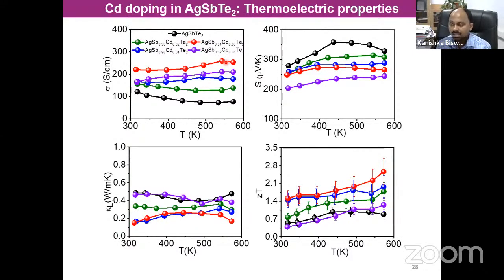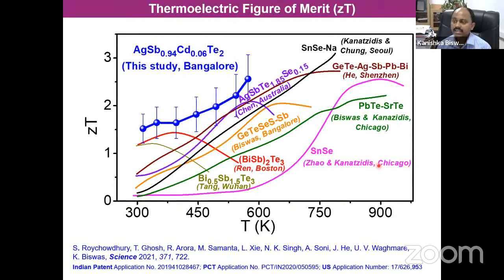And with that, we have estimated the ZT. And you can see the ZT at room temperature is around 1.6, which is one of the highest at room temperature. And it goes to around 2.6 at around 570 Kelvin. So then I compared ZT with other materials which are state-of-the-art in the field of thermoelectrics. You can see in this mid-temperature range, this material actually outperforms all the materials which are discovered till now.